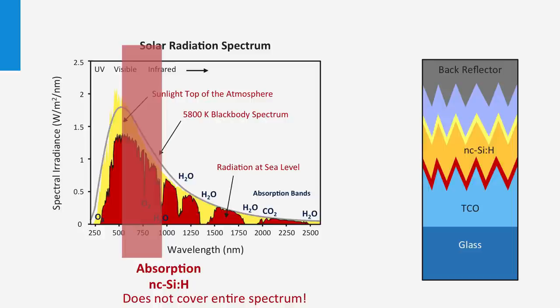Nanocrystalline silicon films are used as an intrinsic absorber layer in a p-i-n solar cell as well. The spectral utilization of the nanocrystalline silicon p-i-n junction is better than amorphous silicon due to its lower bandgap. However, to utilize the spectral part from 700 up to 950 nm, thicker films are required. Typical intrinsic film thicknesses are 1 up to 3 microns. Maximum short circuit current densities of 30 to 31 mA per cm² have been demonstrated by United Solar in the United States. The highest open circuit voltages are around 600 mV. The record conversion efficiency for a single junction nanocrystalline silicon solar cell is 10.7%, achieved by EPFL in Neuchâtel, Switzerland.